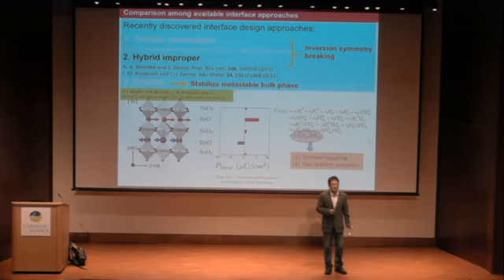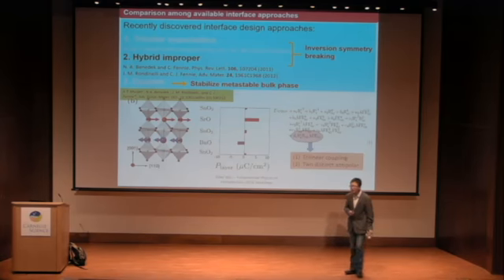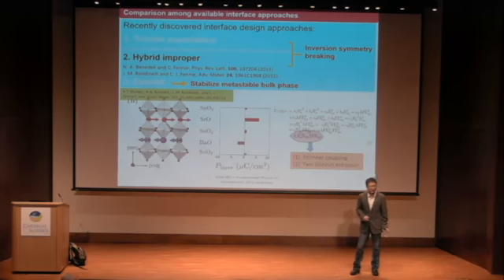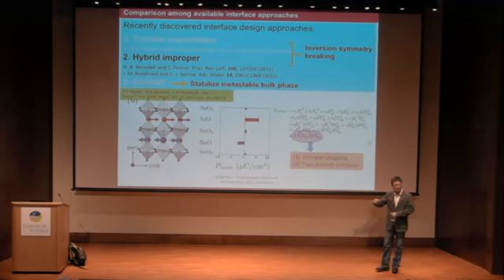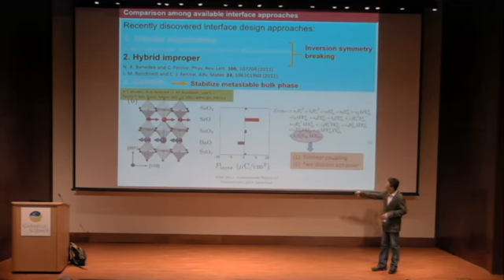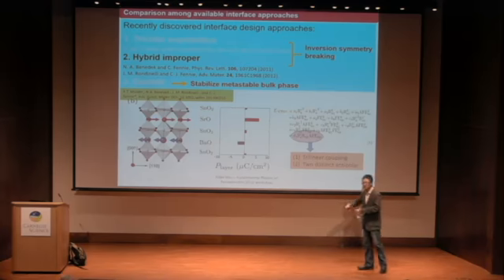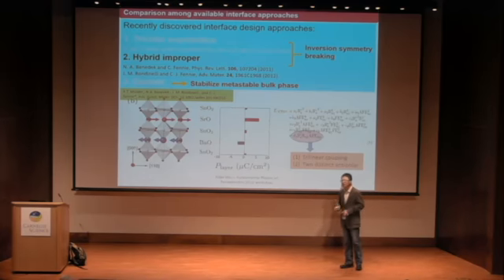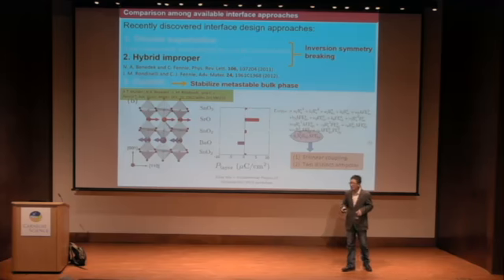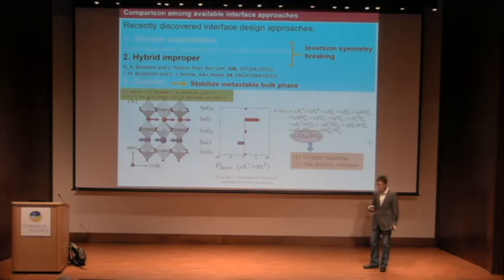Then what's going on in hybrid improper? Hybrid improper actually uses this trilinear coupling term. You have two different bulk materials with two different coupling constants and two different antipolar modes. This antipolar mode doesn't cancel at the interface, giving you a non-zero polarization. So that's what's behind hybrid improper.